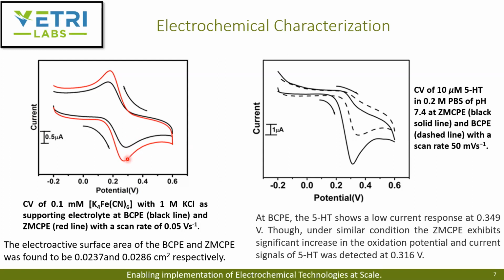So the zirconia oxide nanoparticles are very active, and they are able to oxidize and reduce the potassium ferrocyanide complex. They found the electroactive surface area to be about 0.0237 for the carbon paste electrode, and 0.0286 centimeter square for the zirconia modified carbon paste electrode. To understand the oxidation of serotonin, they used a PBS buffer to adjust the pH to 7.4, and we'll see why they use 7.4 pH in a later slide.